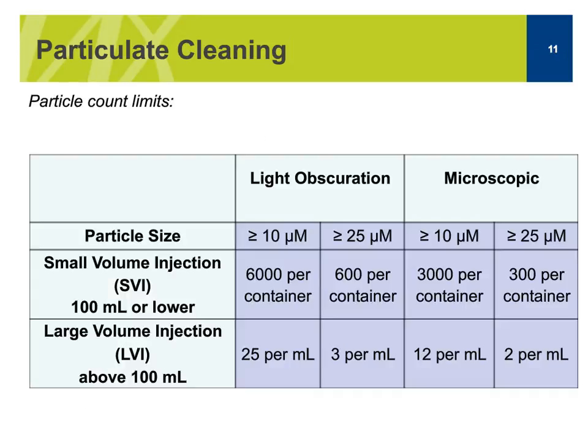This slide pretty much shows the allowable or acceptable particle count test for USP 788. For the light obscuration method, particle sizes that are greater than or equal to 10 micrometers, small volume injections are allowed to have 6,000 per container, where large volume injections are only allowed to have 25 per milliliter. For particle sizes that are greater than or equal to 25 micrometers, small volume injections can have up to 600 per container, and large volume injections cannot exceed 3 per milliliter.